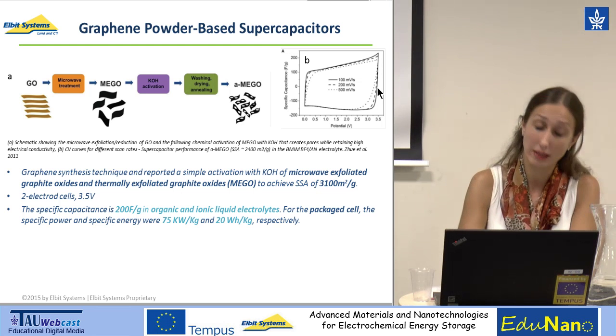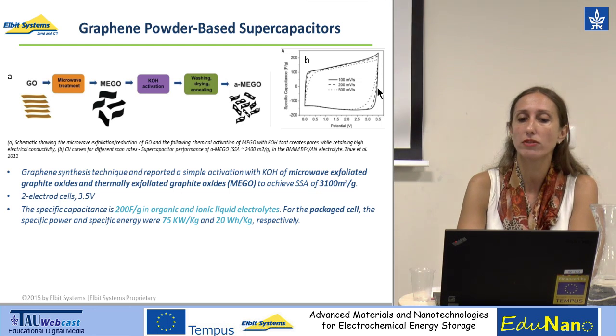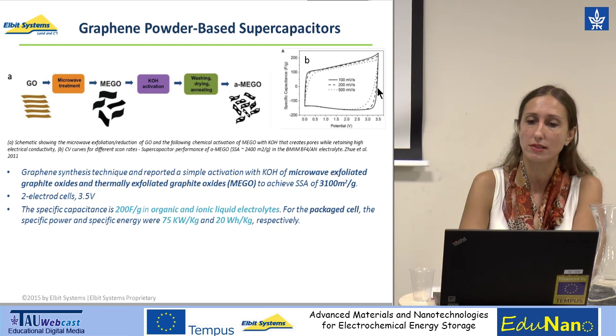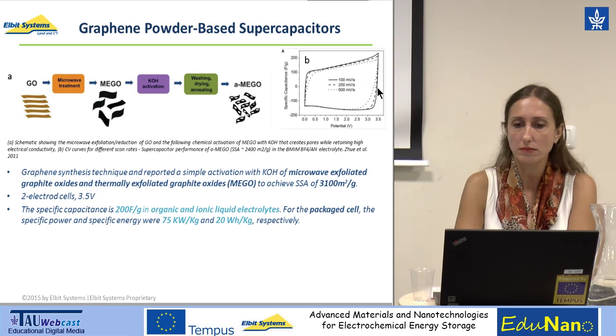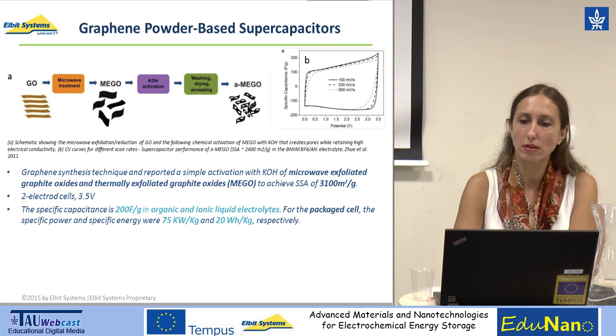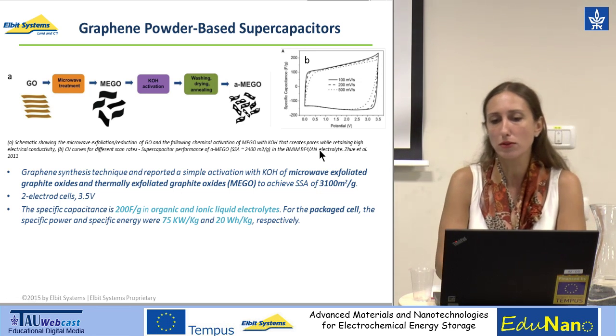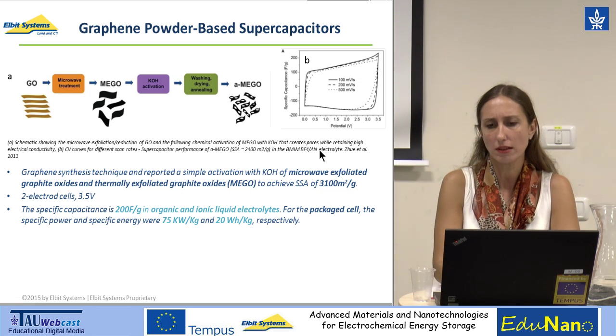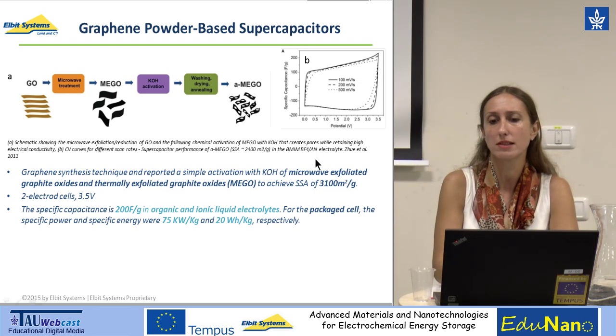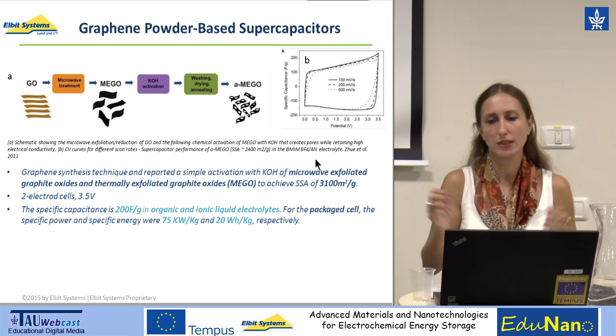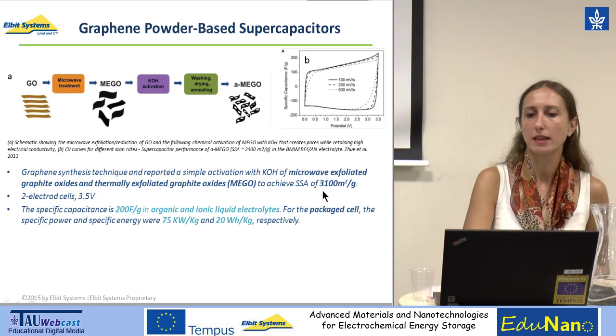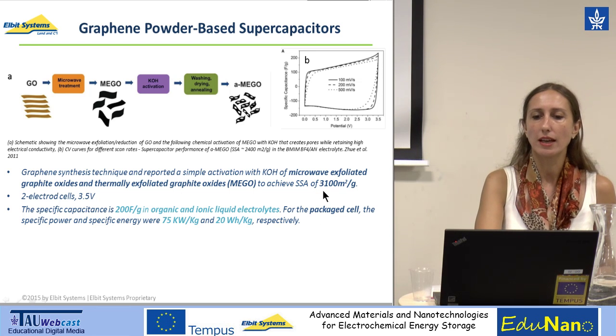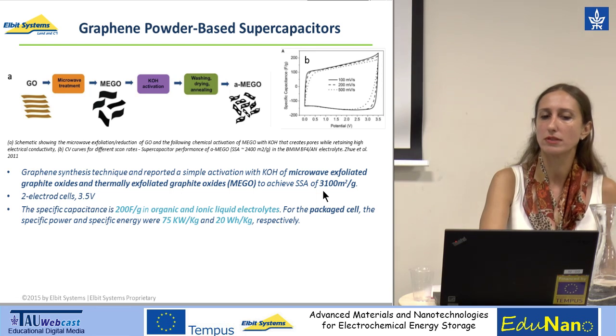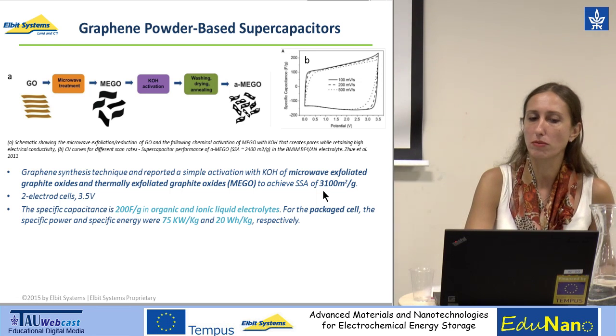extended, so the electrochemical window is enlarged, probably due to the functionalization and due to the specific electrolyte that is being used here. It is not a pure acetonitrile electrolyte, but it also has the implementation of some specific salts in order to prolong or to extend the electrochemical stability of the electrolyte itself. It's an ionic liquid in the end of the day, so what you see here is the extension of the cell voltage at 3.5 volt, and